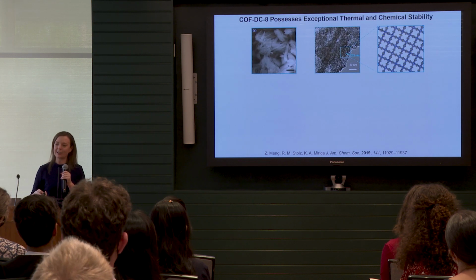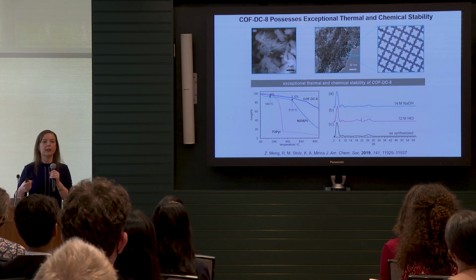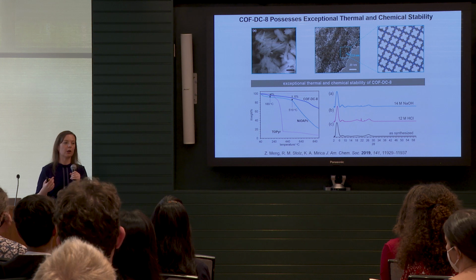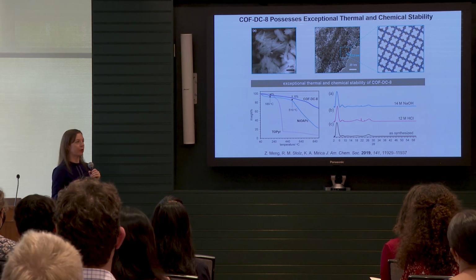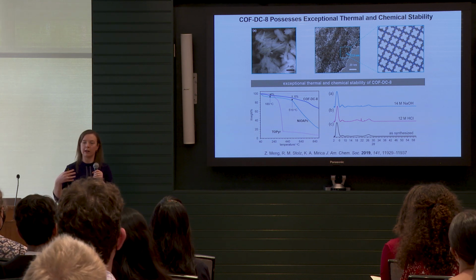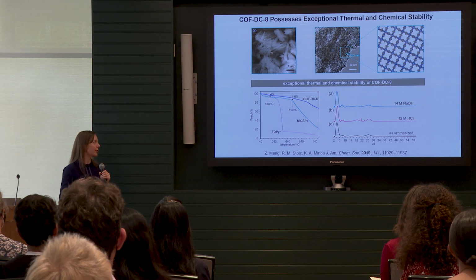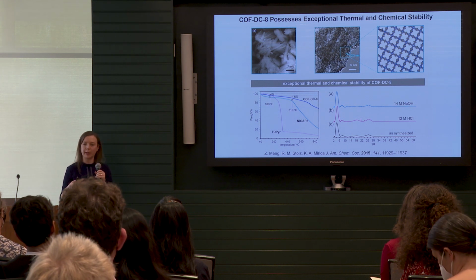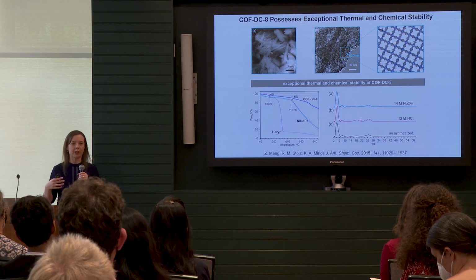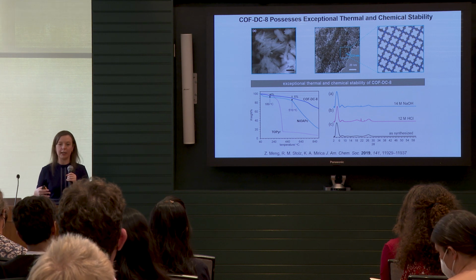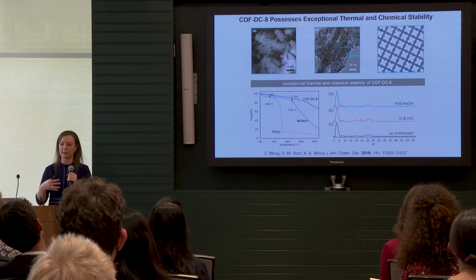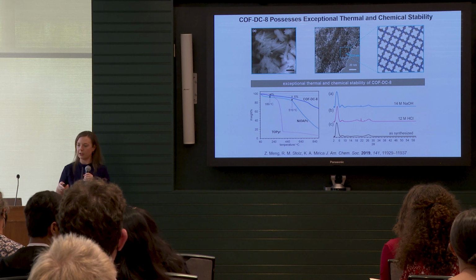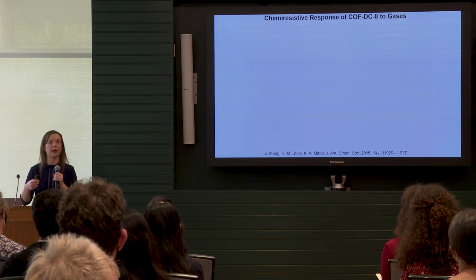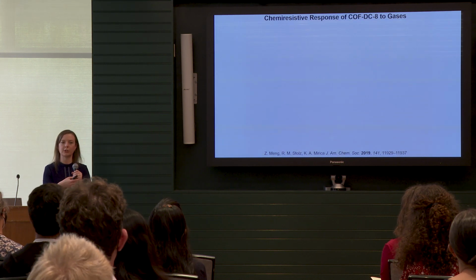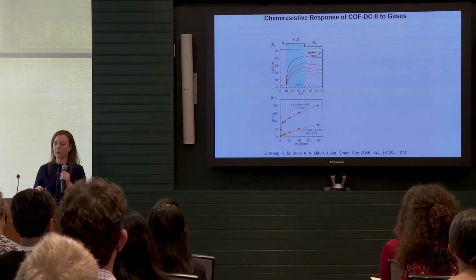It's also a crystalline material. We can characterize it. It's extremely robust. So compared to the metal organic frameworks that I talked about, which are already very chemically and physically robust, this particular material maintains its structure in the presence of concentrated acid and concentrated base, and does not decompose until 500 degrees Celsius. So it's very chemically robust, owing that robustness to the chemical structure that we employ.